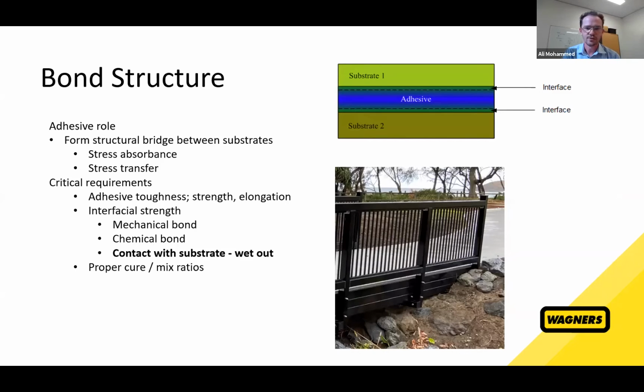So the adhesive bond itself is formed of typically the substrates, which are the materials that you want to bond together, and then the adhesive. And obviously, it forms a sandwich of the two substrates and the adhesive in between. The area directly where the adhesive touches either substrate is called the bond interface. So the role of the adhesive is to essentially form a structural bridge between the two substrates, and that takes the loading conditions and also transfers the stress from those loading conditions between the two substrates. So effectively, you want to join two substrates together to form a cohesive material via this adhesive.